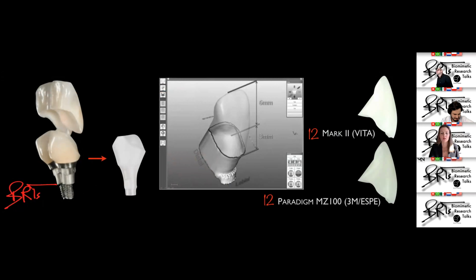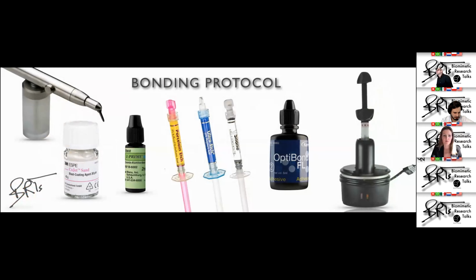And once the zirconia abutments got to USC, they directly replicated those 12 ceramic veneers, those 12 composite resin veneers that were bonded together using a strict bonding protocol, using sandblasting with CoJet. Then the parts were cleaned and put in the ultrasound bath. And once the zirconia was dried, they applied 2 coats of Z Prime, gently air dried, light polymerized, and then the veneers were prepared and they used adhesive Z100, preheated Z100 as the bonding agent.